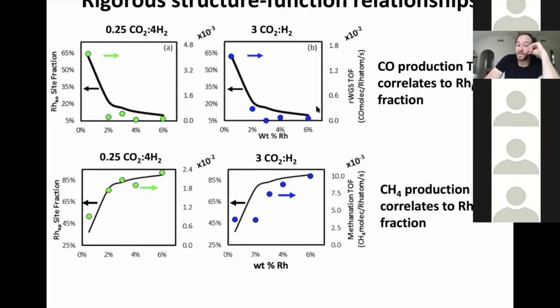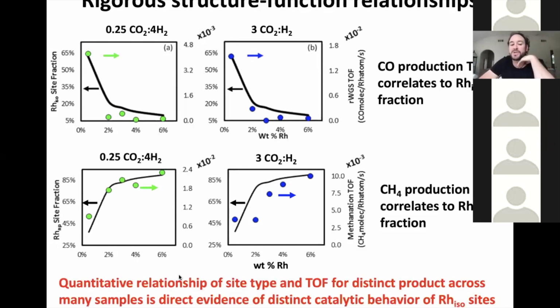Similarly, you can do the converse, where you relate the fraction of sites exposed on nanoparticle surfaces to the turnover frequency for methane. This is the other reaction that we could see happen. And once again, we have nice quantitative relationships. So this tells us together that we can quantitatively relate the turnover frequency for each product in this reaction to the two different types of sites we have.